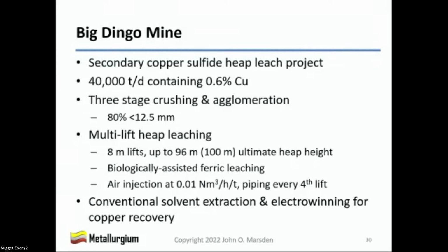He was pretty happy with what he saw from the test work results. Now, the copper was mainly present as chalcocite with minor amounts of oxide copper and primary copper sulfides. Can anybody see what's coming? The average of the column leach test extractions was 79% after 180 days of leaching. Now, he realized that the corporate metallurgist had insisted on applying a 96% scale-up factor to these recoveries, and he was pretty happy about this because that was one of the tough lessons he'd learned at Cherokee Creek. Now, acid consumptions were moderate, ranging from 4 to 8 kilograms a ton and averaging about 6 kilograms a ton.